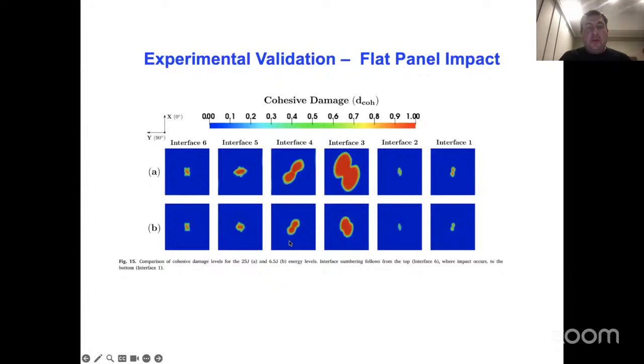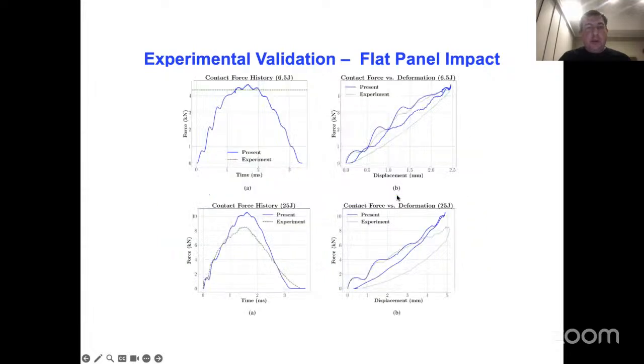Here we're looking at the 6 different interfaces, and these are delamination patterns, basically contours of the cohesive damage. You see the typical peanut-shaped delaminations as you would observe in this case, although it is well known that interfaces toward the back tend to generate more delaminations, but we're not capturing it in this experiment.